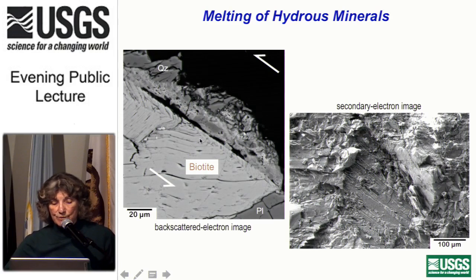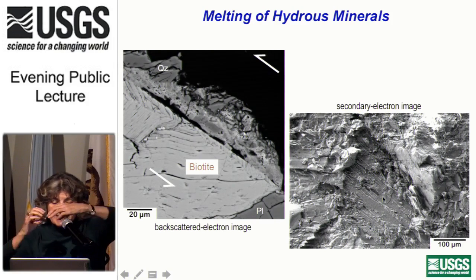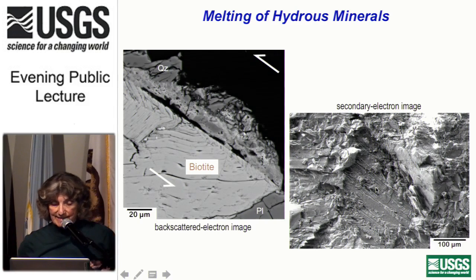And this is where we change views now, going to secondary electron images, and we're going to be looking down on the surfaces of the fault. This is one of those images. The topography that you see here, these were the bits of mineral fragments that broke off from the other granite block and got stuck to the glass on this piece here. This lower area corresponds to, say, the cross-sectional view along the fault plane of one of these biotite crystals. And you can see all this streaking and lines and extended things that show the slip direction during the motion, this stick-slip event.